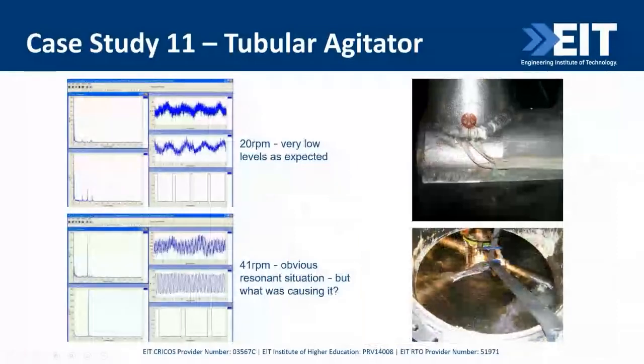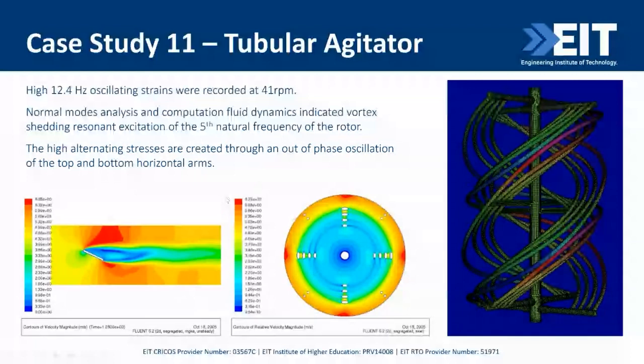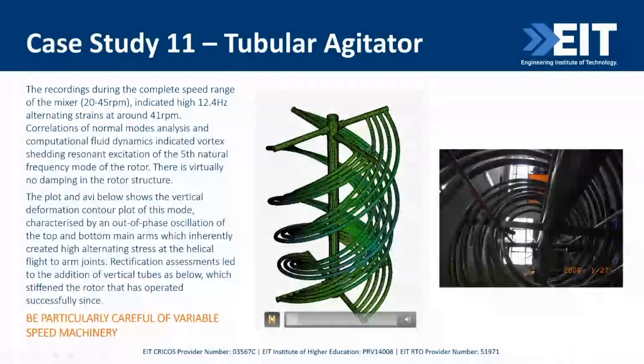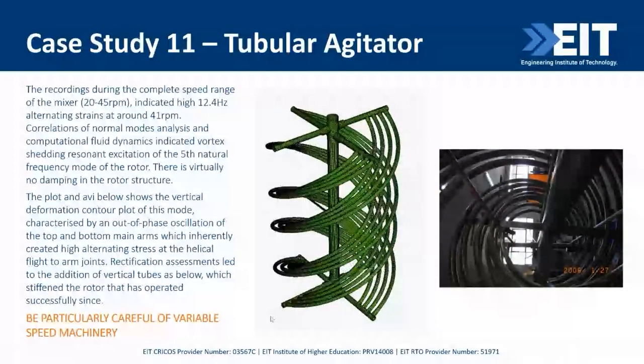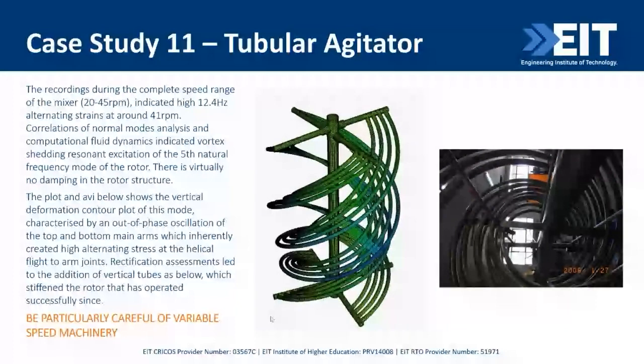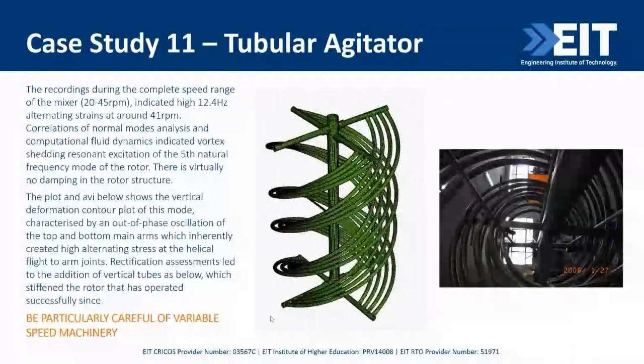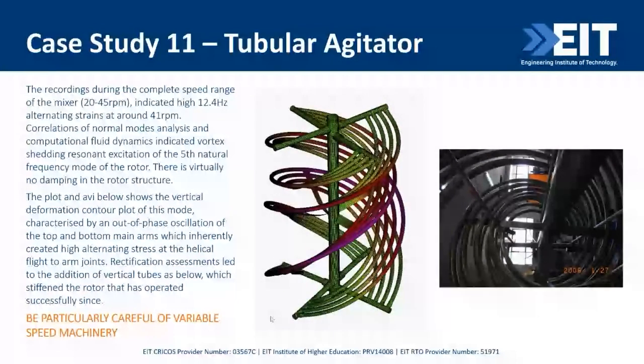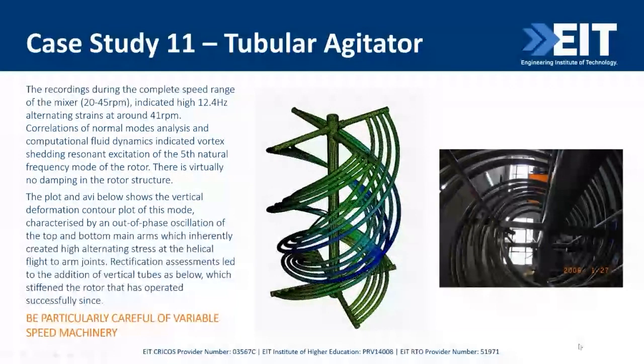So obviously troubleshooting was needed, and what it showed was a huge increase in alternating strains at 41 RPM. Low revs, great, but 41 went through the roof, and that was vortex shedding exciting the 5th mode. This thing again has no damping. That's the 5th mode excited by vortex shedding at that 41 RPM, and there's no weld, however perfect, that can handle that. So the solution was a very basic one: clamp vertical tubes in there, clamped so you didn't make a stress hotspot with them, and that knocked out that mode.